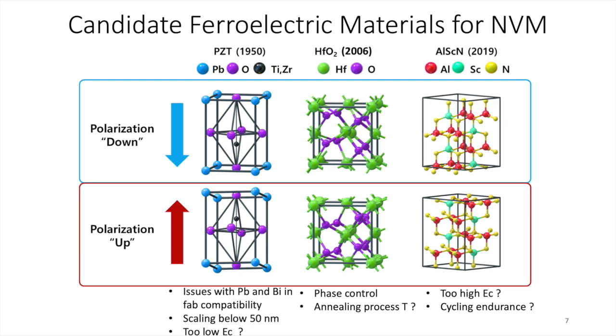The other one is hafnium oxide, which I would say is quite advanced today. Many industries are thinking of deploying it, but it also has its own challenges. Getting into the right ferroelectric phase over entire process wafers in a reliable way, at processing temperatures that are compatible again with back end of line, is very challenging. This has prevented hafnia from being deployed, even though the first ferroelectricity in hafnia was reported back in 2006.